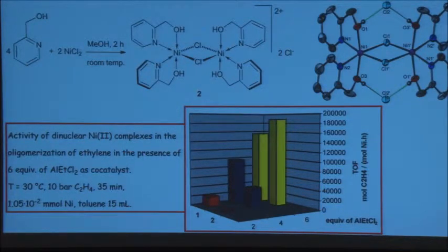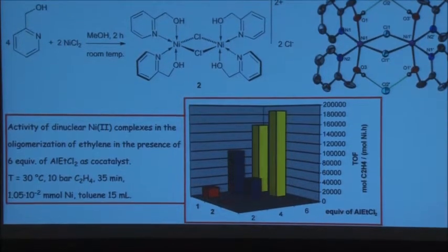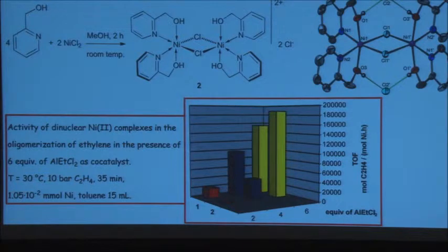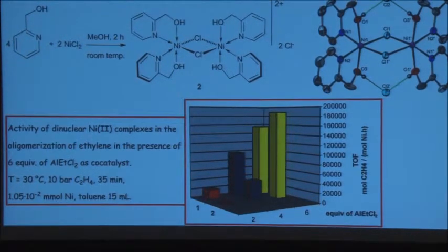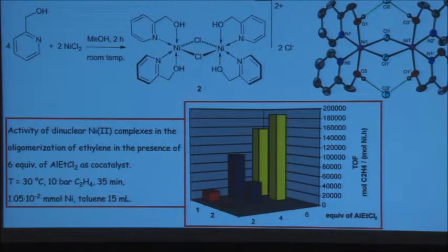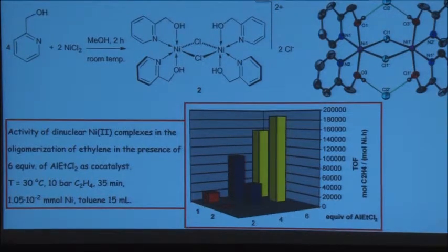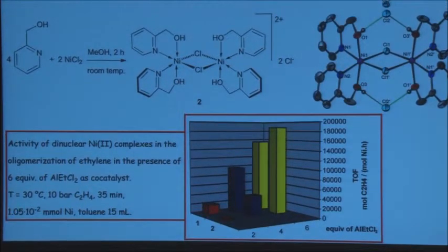But it's a very expensive drying system, not very green, because at the end of the day, you hydrolyze your co-catalyst and you produce mountains of alumina. So what do you do with the alumina? Also, these co-catalysts are quite expensive. So our challenge is to use as little co-catalyst as possible.